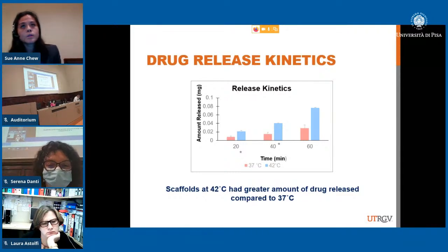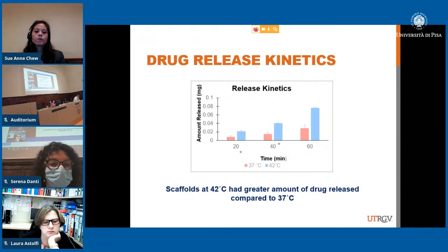So the next thing we did was we wanted to see how the drug release changes when we go from a 37 physiological temperature to an elevated temperature of 42 Celsius. And as you can see here, the blue bar, there was an increase in the amount of drug that gets released compared to the 37 physiological temperature. So, as expected, we are able to control the amount of drug getting released when we provide heat to the scaffold, and this is due to the